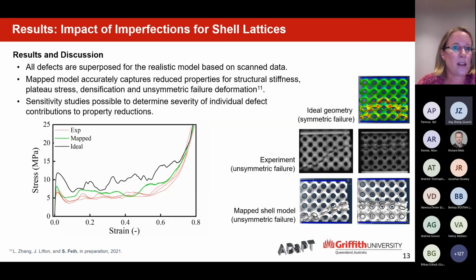Some other impact here that we see for the shell lattices. Again, all defects are superposed, and we see that we can easily reduce the stiffness and the plateau strength by introducing the defects I mentioned. What we can also see is that the experimental results are much more closely followed in terms of unsymmetric failure mechanisms compared to the ideal finite element model. And again, we can do sensitivity studies via our shell element approaches.